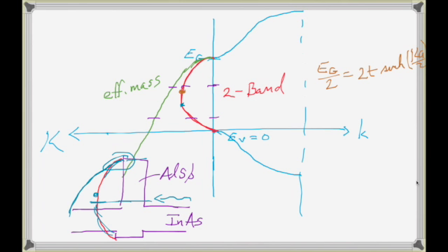We've talked about the parabolic model, then we talked about solving the parabolic model using the finite difference approach, where we discretize it, and we showed that gives exactly the same result as your single band tight binding model. They give you this identical cosine band dispersion, either doing finite difference of the effective mass or single band tight binding. And people back in the 80s used to argue and say, I'm doing a tight binding model, and therefore it's more accurate than finite difference. Actually, that's all the same thing.